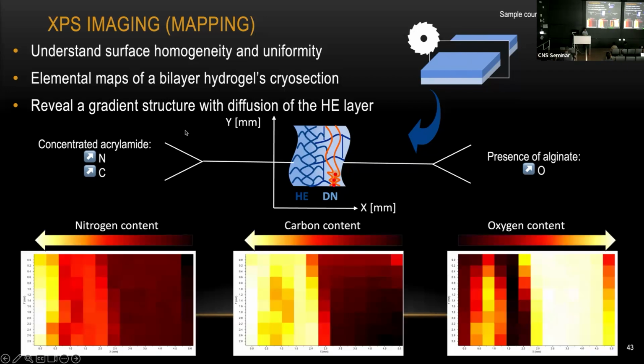And here's a map for the nitrogen signal, carbon signal, and oxygen signal. For carbon and oxygen, you don't see much difference. We simply have a lot of carbon on one side and very little carbon on the other side. But for nitrogen, we do see some kind of gradient from one side to the other side. She went ahead and did some theoretical calculation, and it looks like the data we got here is within a 1% error between her calculation and the measurement. So we can see a nice gradient for the nitrogen signal diffusing from one layer of hydrogel to the other layer of hydrogel.